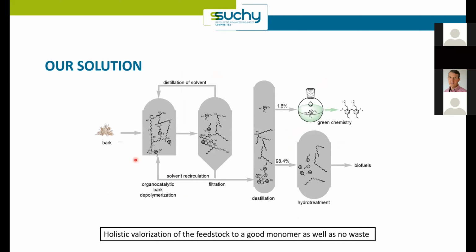So the birch bark, we could fractionate this. So this is birch bark. It's a big polymer, and we could apply green chemistry to break the chemical bonds, and we could liberate the chemicals. And what we did was we applied recirculation instead of distillation of the solvents. And this was crucial for sustainability. So we could come down below 3:1 solvent to wood ratio before we distilled it.